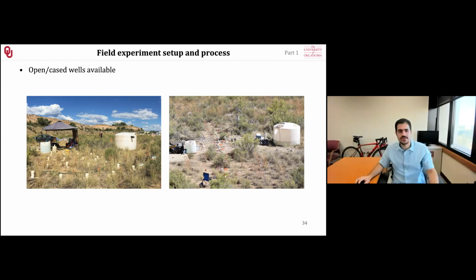We know the groundwater direction here. The groundwater direction is from this side to this side. So we started injecting through wells available around here, and groundwater took all the ingredients with it, and then we withdrew from the down gradient wells here to make sure that we are not contaminating the subsurface with too much ammonia. So we injected here, we collected here, and we assumed everything is happening in the middle here, just like what we had in our columns. For that purpose, we laid out our electrical resistivity and induced polarization array on the surface on 3 lines here, and we were able to collect data on a daily basis.